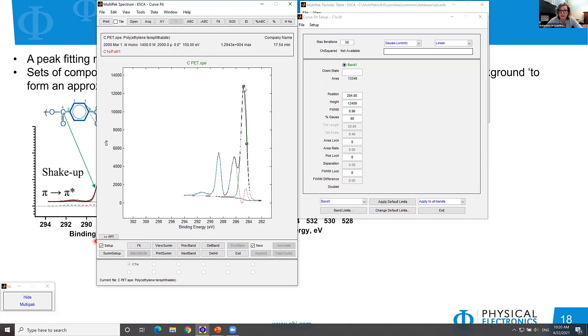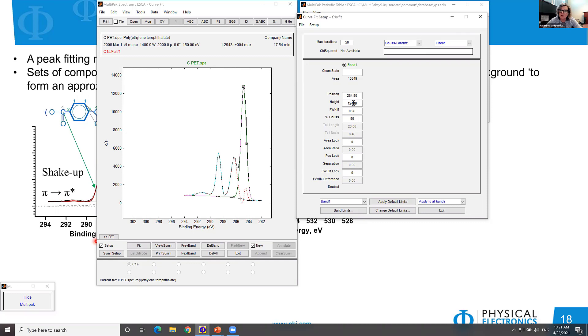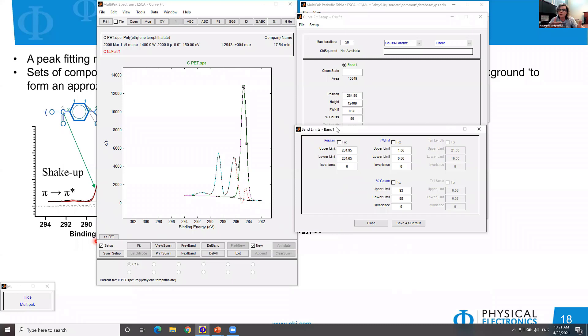We know the biggest peak is the carbon-carbon bond, so I put in the first peak. We can see our first peak added, and the parameters I mentioned: position (binding energy), FWHM, intensity, and the Gaussian-Lorentzian character — in this case set at 90% Gaussian. We also have band limits — the constraints that allow the model to fit peaks within a certain range. Position is constrained to ±0.15, width constrained to ±0.1, and we have a limited range for the GL character.